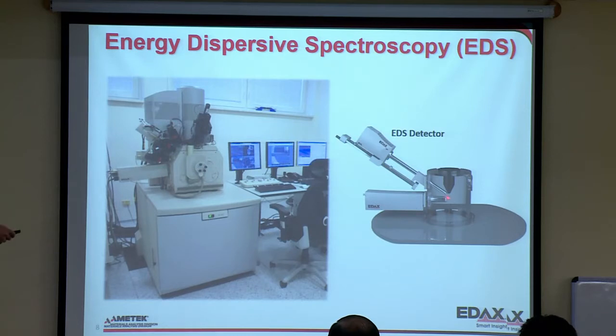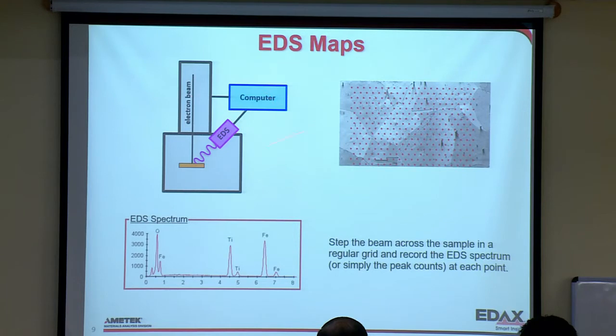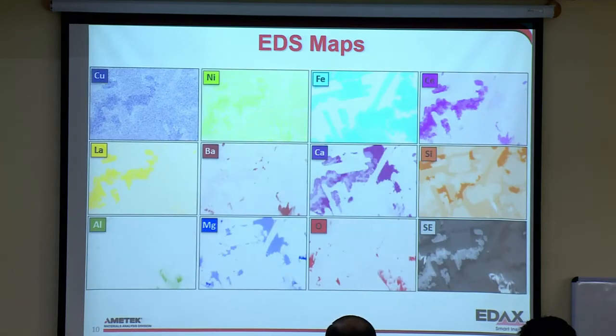So EDS, here's a typical configuration, EDS detector, capturing those signals. And so you can create EDS maps if you control the electron beam and track the EDS signal with an energy dispersive spectrometer. Then you get an idea of the spectrum at every point, and you can map out the composition of your material. Just as an example, here's some EDS maps from a sample. Here's what the secondary electron image looks like, showing the topography of the material. And then we have all these different signals. And you can see then where different chemical species are in your material.